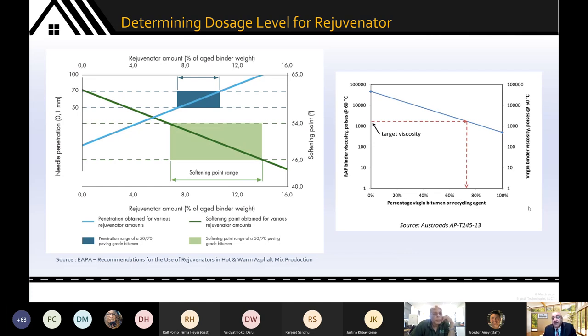You are looking to find out what is the target range, what is the sweet spot in terms of viscosity for your liquid bitumen to perform in the presence of RAP binder and in the presence of virgin binder. And so it's simply a dosage calibration curve based on viscosity. I must also point out, and I don't have examples of this, but in North America, again,